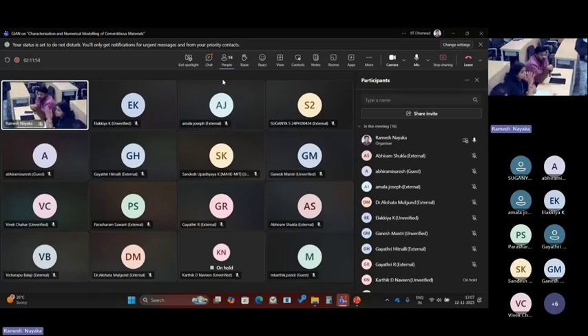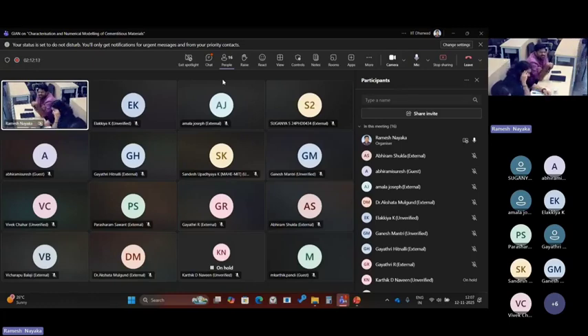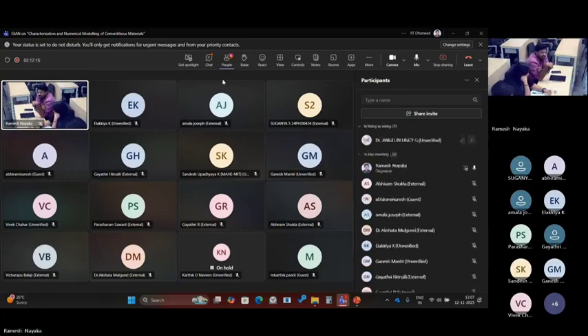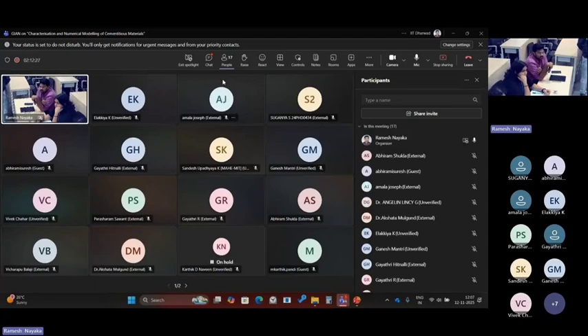Yeah, but again, there are a couple of challenges you would face. There are cases where they have already done it with geopolymer concrete, but you should always be careful about the alkali activators and the setting. If it sets hard while pumping, then you have to pay a lot for your pumping systems and the 3D printer. If you go with lower molarities, we can achieve it. There is no problem. You can try, but this is just my suggestion. If you are able to try that, you can try. There are already cases of geopolymer concrete, and a couple of structures have already been built by adopting 3D printing.